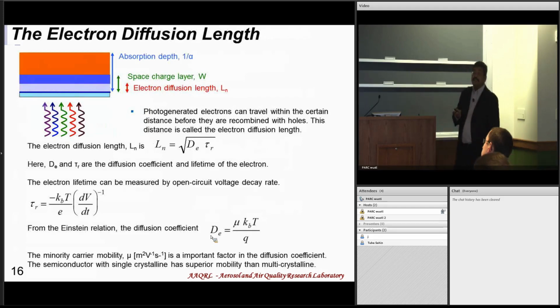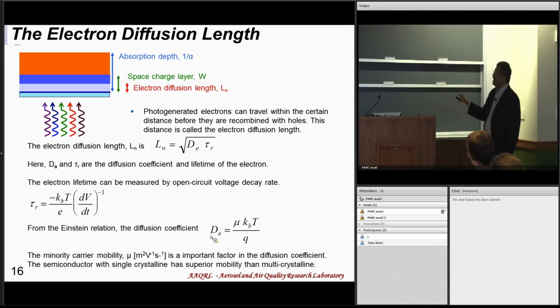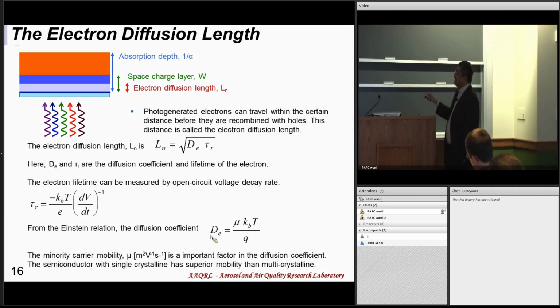Then there is the electron diffusion length. Once I separate it out, there is a certain characteristic diffusion length, and that depends on a diffusion coefficient times a certain lifetime, and of course the square root of that. These are all characteristic dimensions. I can calculate these by doing experiments. There are ways to do electron lifetime measurements by just measuring the open circuit voltage decay rate. You can also estimate the diffusion coefficients. It depends, again, on the material and the transport characteristics.